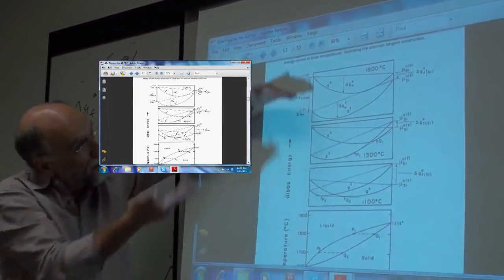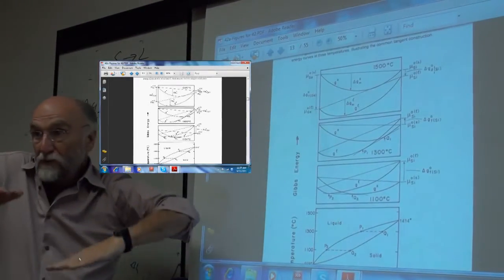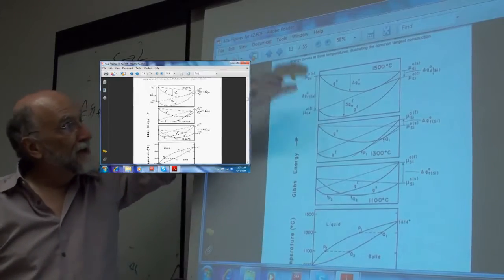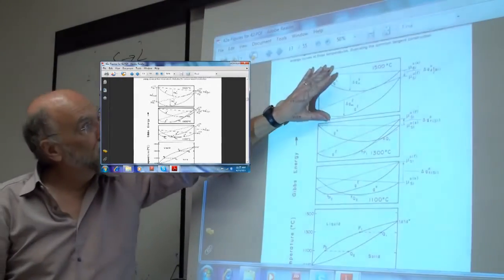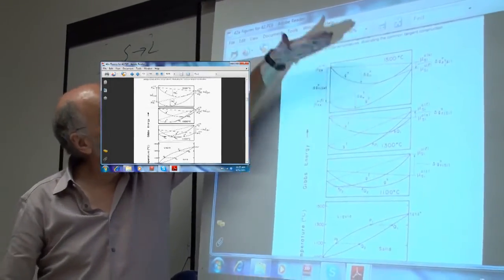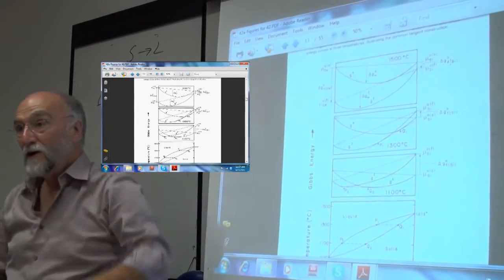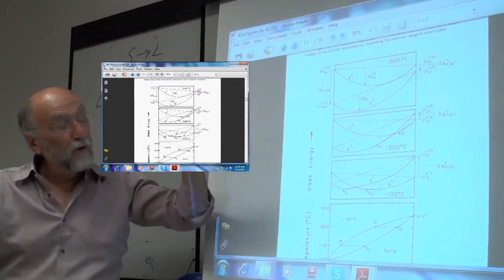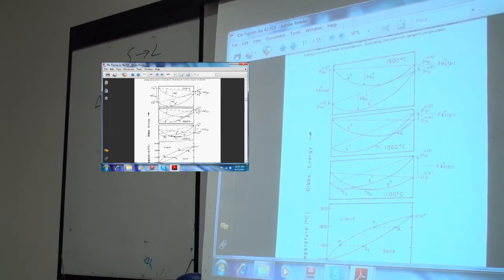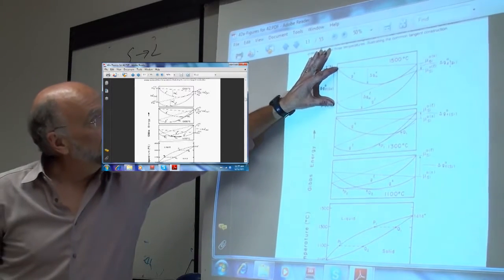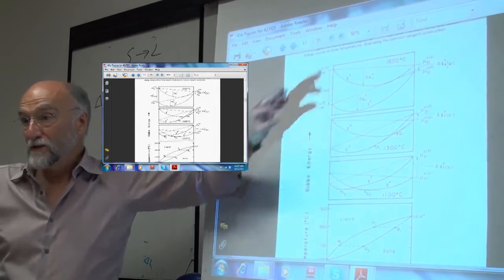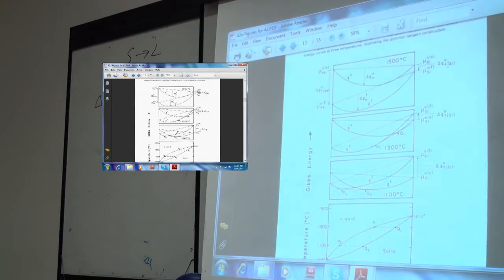So to a first approximation, what simply happens, you can imagine, as you lower the temperature, is that these two curves move closer to each other and cross. It's only the relative distance that matters, so you can think of the liquid as constant and the solid curve moving down. As it moves down, it changes its form a little bit and so on, but the main point is it just moves down because these Gibbs energies of fusion at the ends become less and less and eventually become 0.